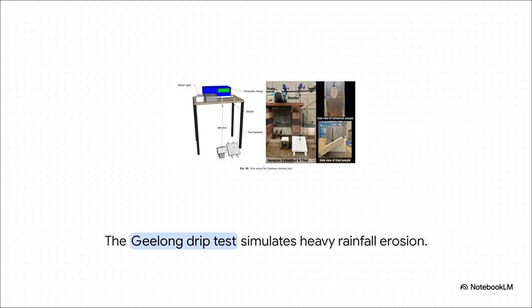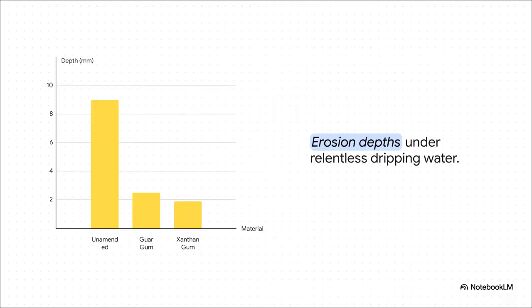In this test, water is actively pumped and dripped directly onto cylindrical and tiled earthen samples from exactly 400 millimeters above. This relentless dripping goes on for a full 60 minutes, and then the researchers measure exactly how deep the water has eroded into the material. The contrast in the data here is just wild. The unamended earth eroded significantly, losing 8 to 10 millimeters of material, but the biopolymers? Both of them stayed well under the critical 5 millimeter threshold.